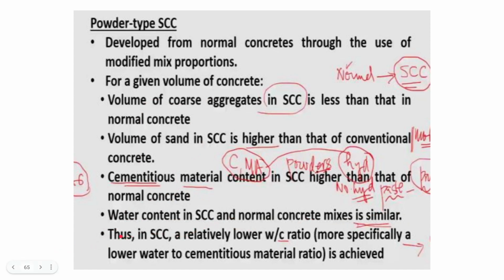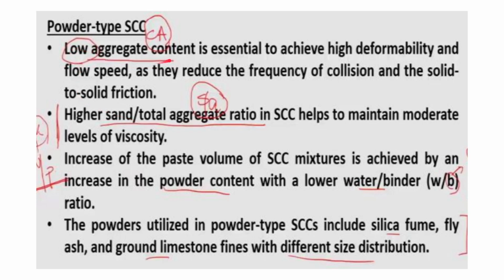Thus in SCC a relatively lower water cement ratio, more specifically a lower water to cementitious material ratio, is achieved. Because we are using powders and superplasticizers, there is a lower water cementitious material ratio, because a lot of powder is there without any effect on the workability. The low aggregate content is essential to achieve high deformability and flow speed, as it reduces the frequency of collision and the solid to solid friction. So that is the benefit of using low aggregate content.